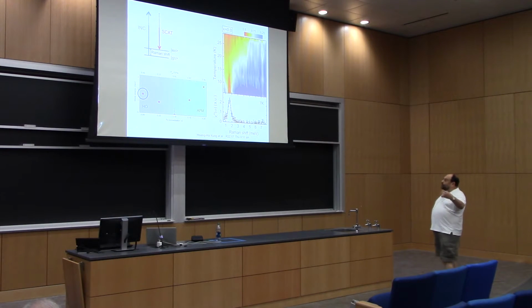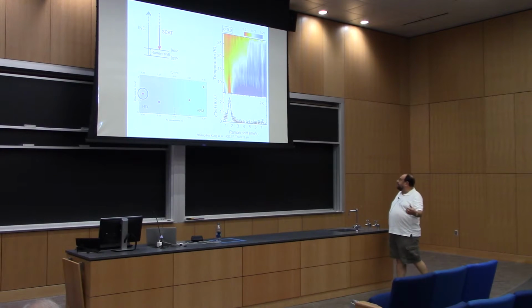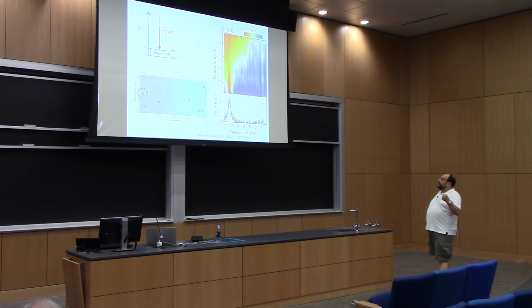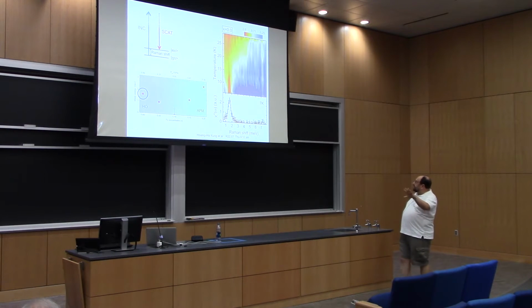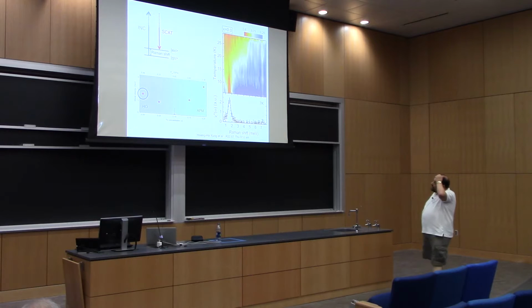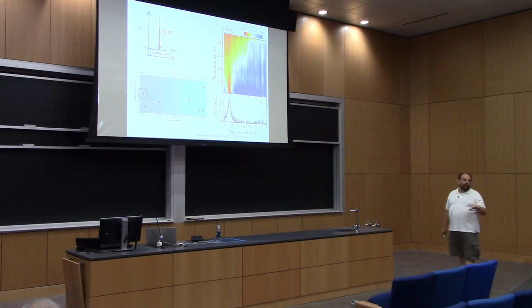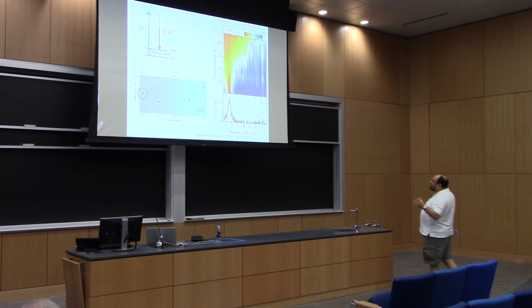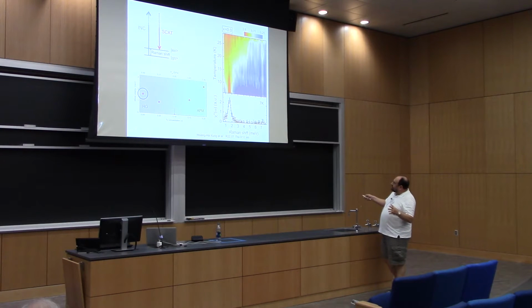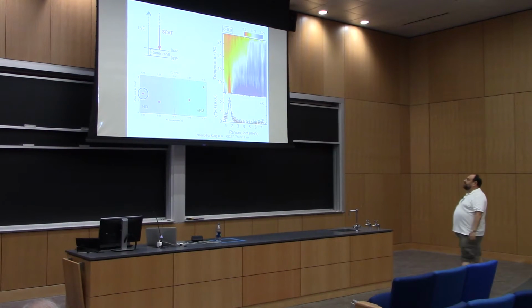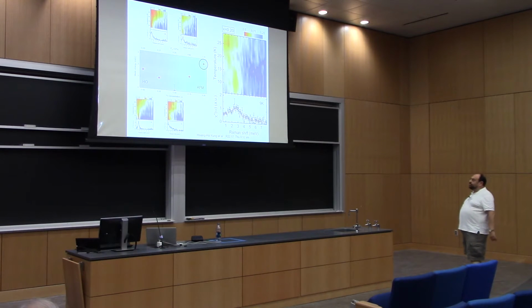So we did the experiment, the one that Sean discussed before the break, on the systems as a function of iron doping. This is data very similar to what Sean showed, except this is now done on samples from Brian's group, and the previous was done on samples from Eric Bauer's group, which had a triple R about 700. Triple R here is not that fantastic, but it still gives a very nice collective mode, clearly beyond noise. There's not much else in the A2G channel.